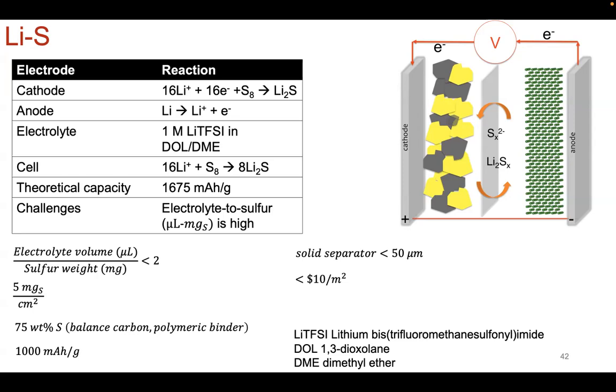And there are several hundred studies that show that, with all sorts of physical barriers that have been added to prevent the polysulfide shuttle, which is exactly shown in the orange arrows that you see here, right? So once sulfur is in the composite cathode, in ether-based electrolyte, you have polysulfides, and you also have the production of lithium polysulfide. And these two species, or sets of species, will migrate. They will shuttle from the cathode over to the anode, sometimes get deposited on the anode, and you form solid electrolyte interfaces that are not always advantageous. You also lose active materials.